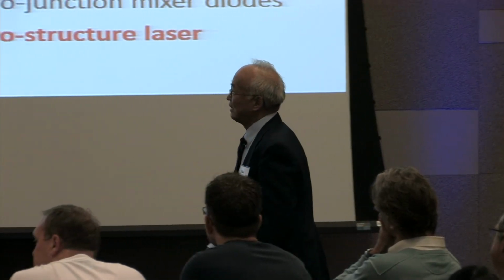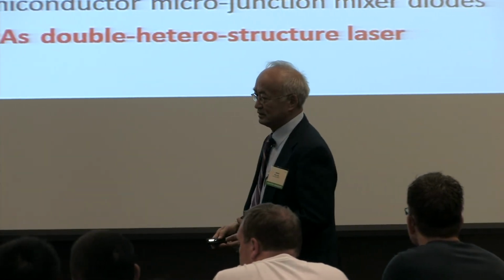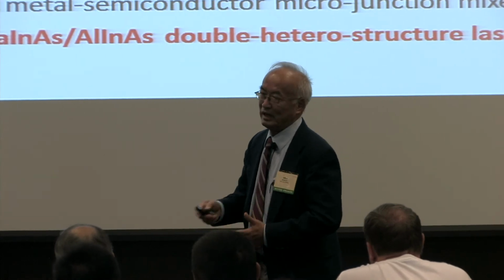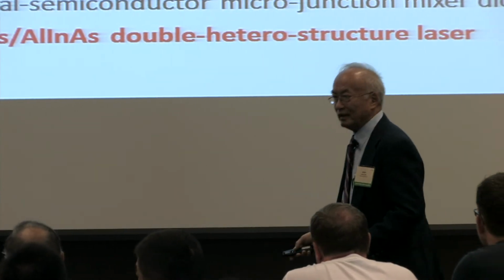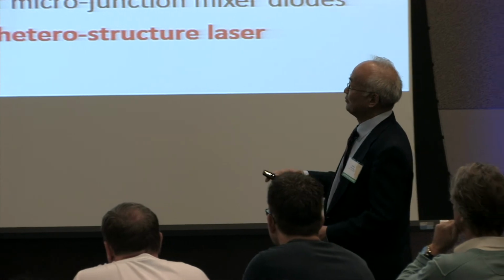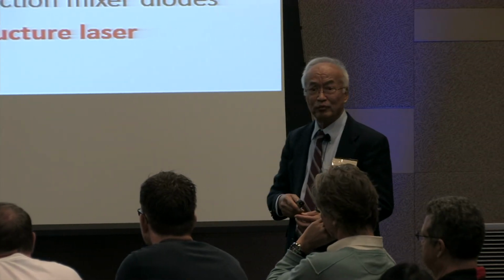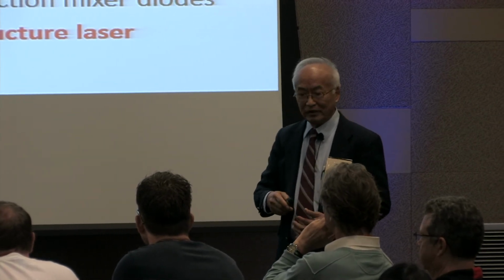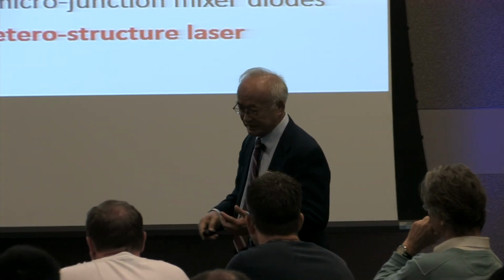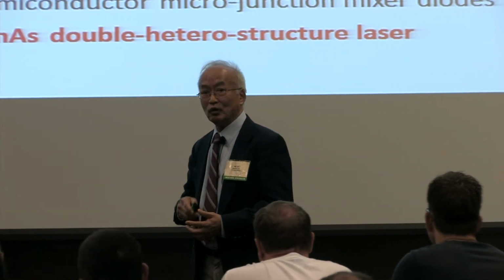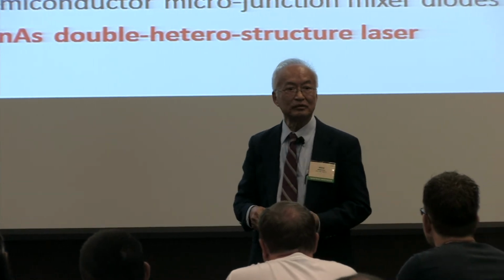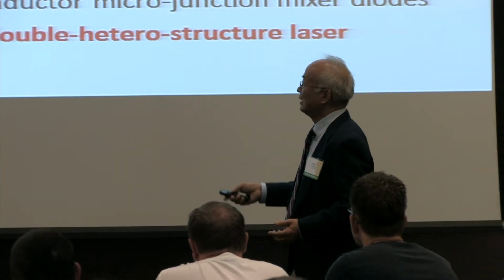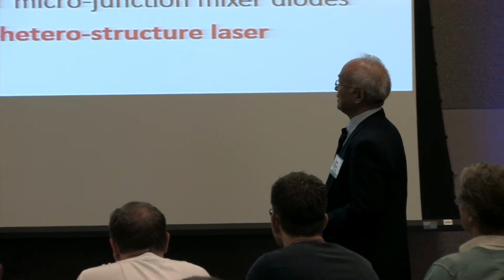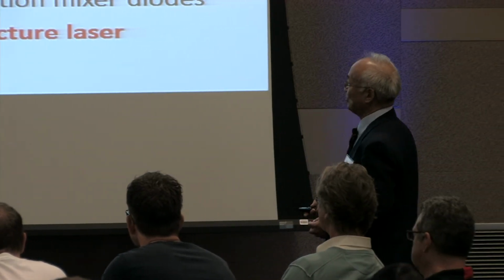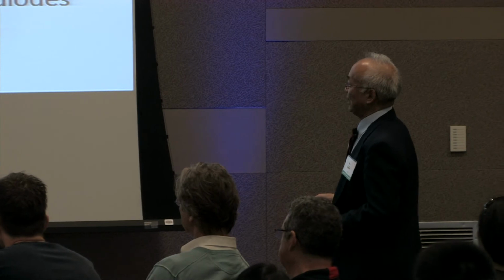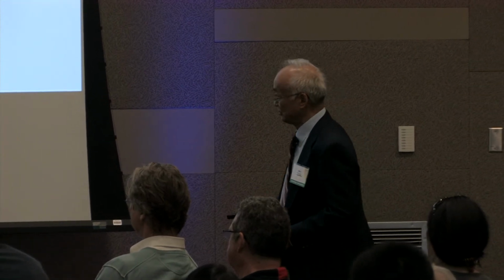By 1980, we go into long wavelengths with Norman Chen in my lab. They're growing III-V compound materials. And then we need to have more uniform growth. With Norman Chen in my lab, we demonstrate the first rotating MBE substrate holders to get more uniform growth. And then we'll continue to make the 1.55 micron InGaAs/AlInAs double-hetero-structure lasers, these room temperature.